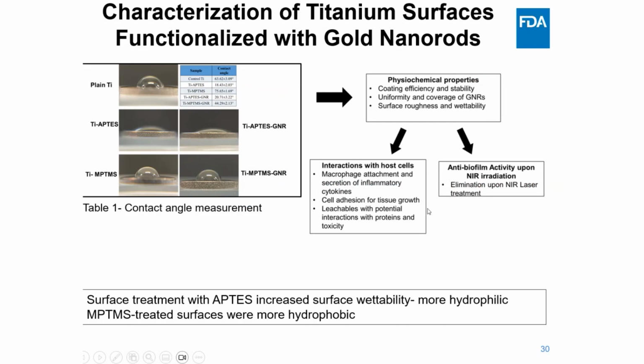So next, we have done various characterization, particularly physicochemical characterization and biocompatibility testing, as well as photothermal activity analysis on these titanium surfaces functionalized with gold nanorods. So to assess the wettability, we measured the contact angles of these functionalized surfaces by placing water droplets on each surface.